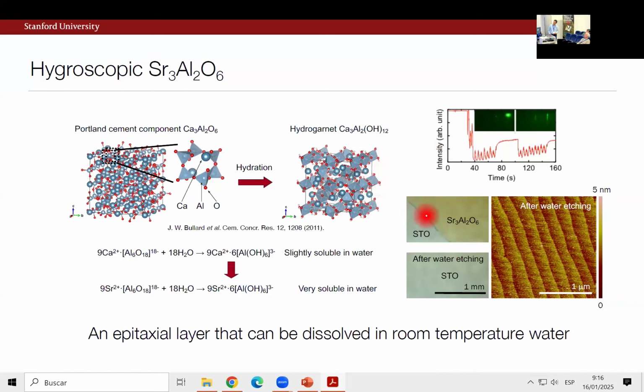And so this is a very early example of just saying we masked off an interface or covered up one layer. This is, say, 100 or 200 nanometers of this strontium version of this material. And just dip it in water for a second and blow it off, and you can see it's completely gone. And these components are very nice because then it gives you a surface that is very residue-free, as far as we can see. So maybe not universal, but quite nice in the sense that this gives you an epitaxial layer that grows well on many of our perovskite building blocks, and it can be fully dissolved in room temperature water.